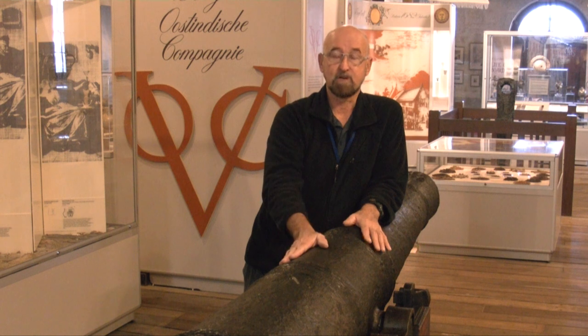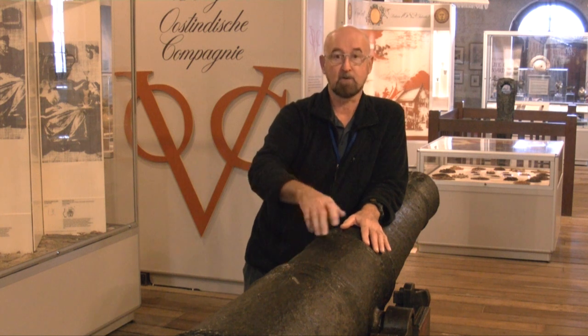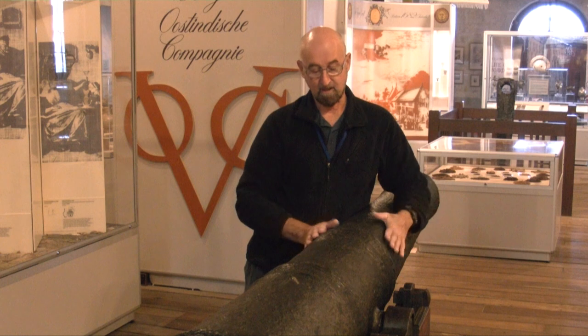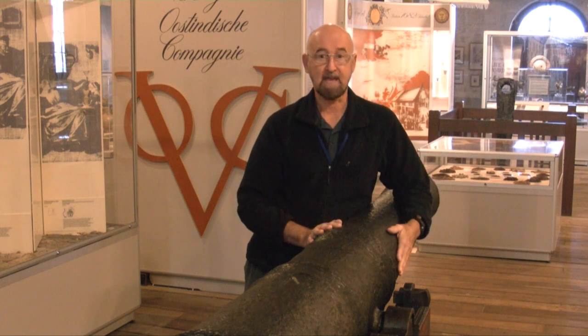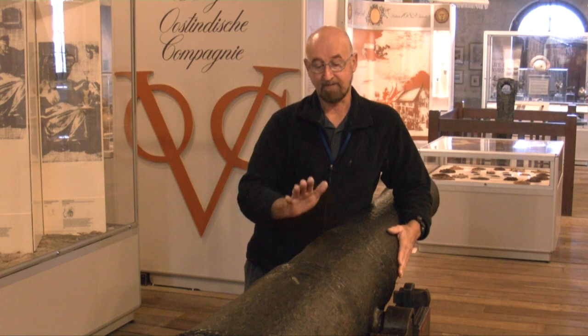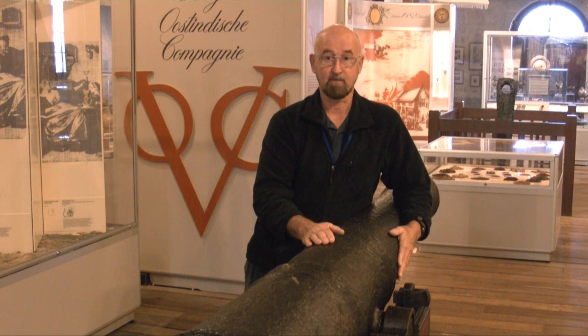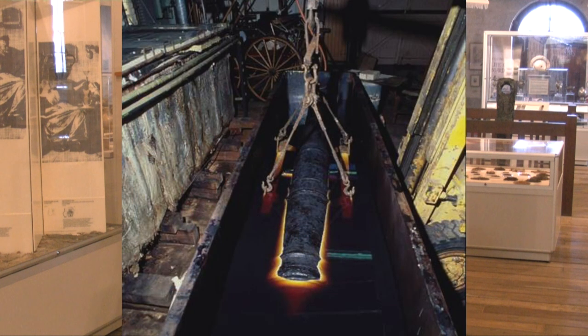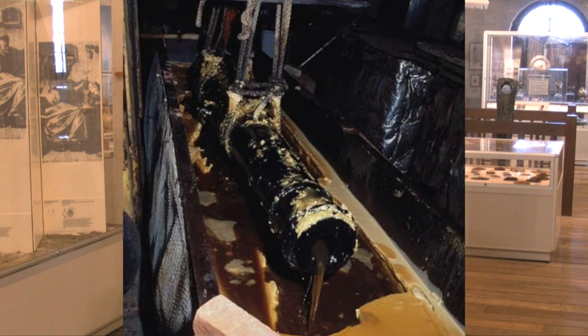The cannon, when it's been treated, is this black colour. The rust inhibitor also enhances that and gives it the appearance that we would accept normally for a cannon. Once that's done, we have to put this cannon in molten wax. We have a big tank of molten wax, and we place it in the wax, sit it there for about a couple of days. The air in the porous surface comes out. Then we turn the heating elements off, the wax begins to cool, and then it drips drawn into that porous surface and consolidates or strengthens that surface.